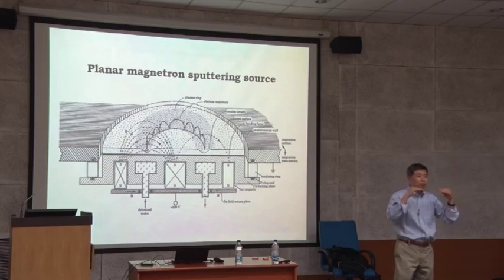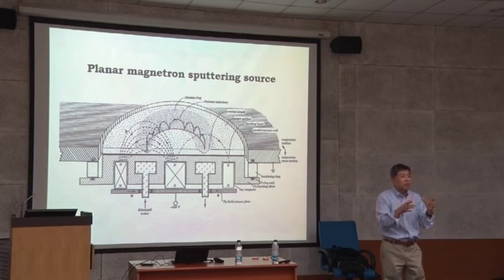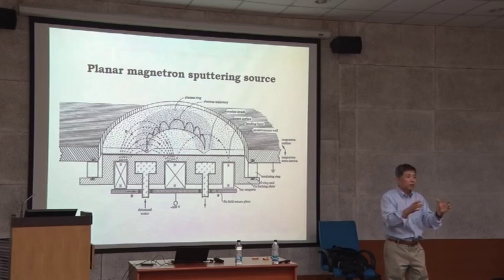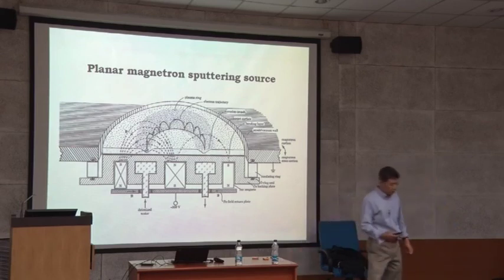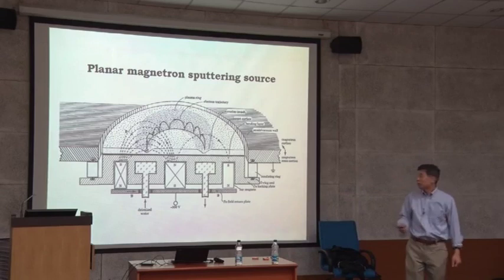And then you cure this, then you can have not only thermal conductivity, you can hold it against thermal expansion, but you also hold it mechanically, clamping. So that's very important. Once you cure it, your target has good thermal conductivity and is mechanically well clamped. Then you can use that. So that's something. Ceramic target, I highly recommend doing that. Metal target, you don't have to do that. Even some metals like manganese can easily be shattered too, so you have to use cups for those metals.